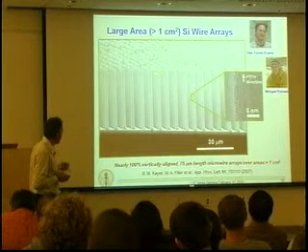However, if you're careful about it, this is a relatively simple process, and it's a nice one for growing wires. Each one of these wires is a high-quality single crystal. And we're able to form wires in dense arrays by growth on a carefully designed template using these metal catalyst particles. The uniform wire diameter also gives rise to a uniform wire length, and so we can make large area arrays that are uniform over square centimeters. Here's another example showing an array that's over square centimeters.